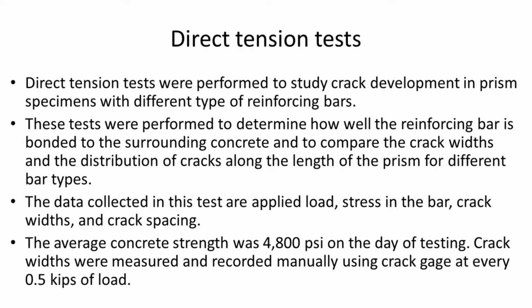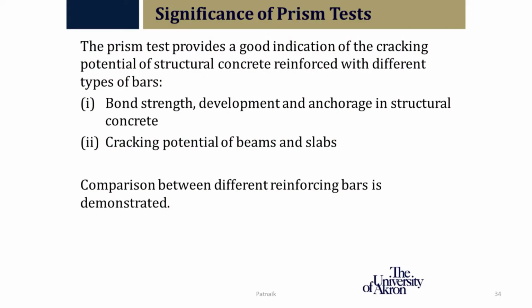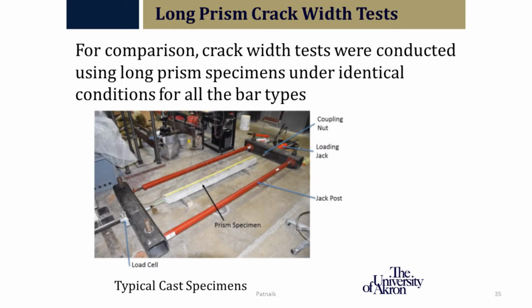So the average concrete strength was 4,800 PSI on the day of testing. There's a lot more data in the report, obviously. I'm just capturing some of the highlights. And they applied this load at every half of a kip. Bond strength development and anchorage in structural concrete and cracking potential of beams and slabs are what's important here. This is the layout of the test. You see a coupling nut at the end with a loading jack, jack post, and a load cell to determine what the actual pull-out strengths were.